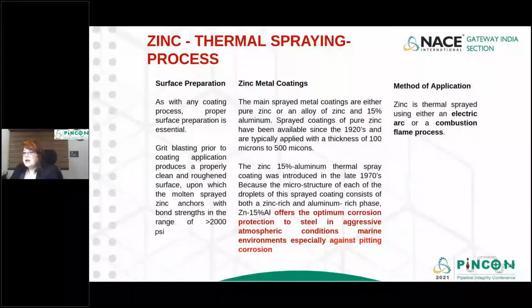In the zinc thermal spraying process, proper surface preparation is essential, as the molten sprayed zinc anchors with a bond strength in the range of greater than 2000 psi. Pure zinc sprayed coatings started in the 1920s and are typically applied with a thickness of 100 microns to 500 microns. The zinc and 15% aluminum thermal spray coating was introduced in the late 1970s.